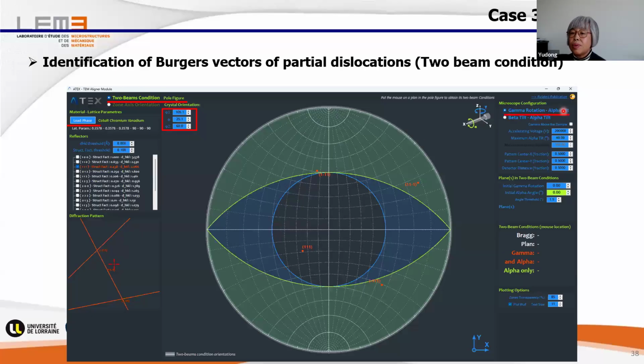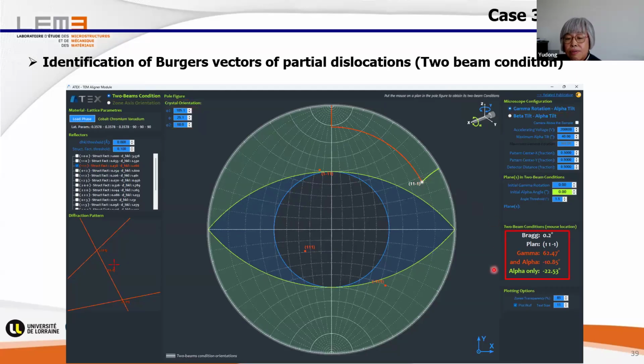And next, we have to select which kind of sample holder order we would like to use. In our case, it's gamma rotation, alpha tilt. And then we have to define the limit. For gamma rotation, there's no limit, but for alpha rotation, we put a 40-degree limit. And now we have to select the reflection plane. So for the first case, we select the 111 plane, and you see it is here, the reflection plane. And so we just need to use the mouse to click on this dot. Immediately, the software calculates the results for you.